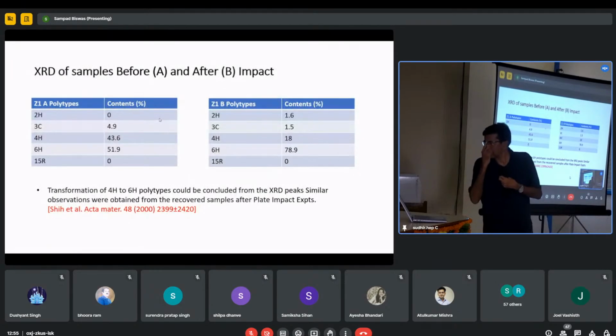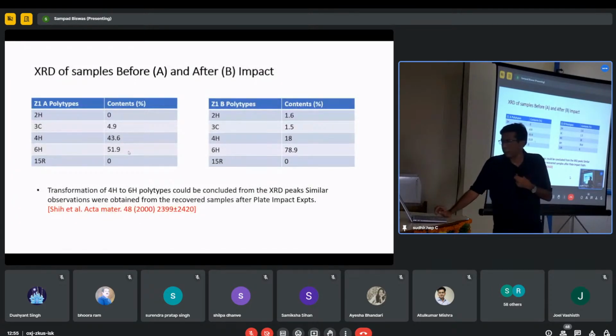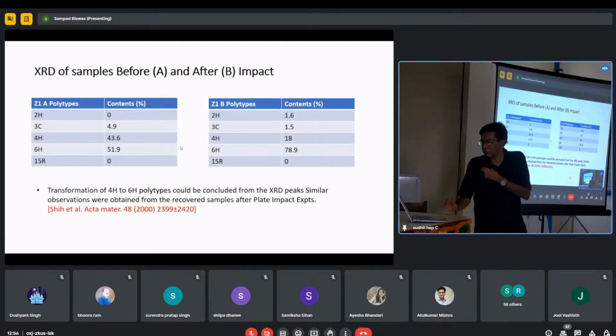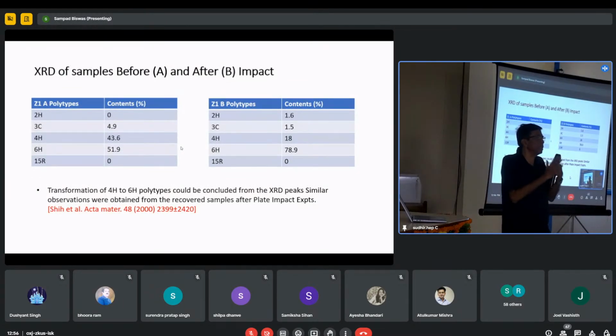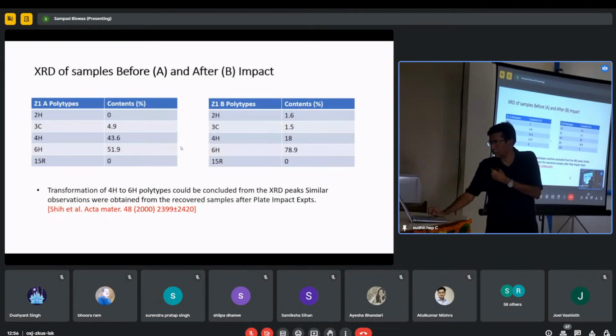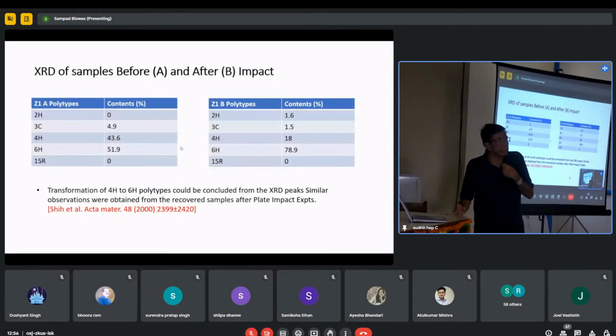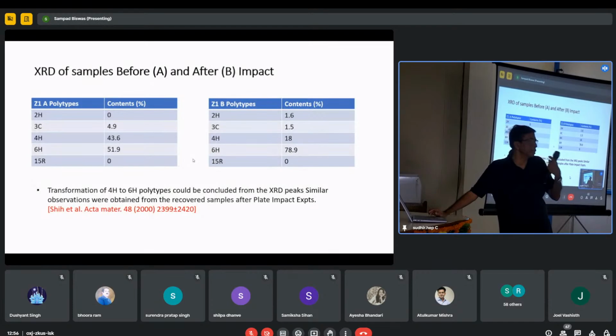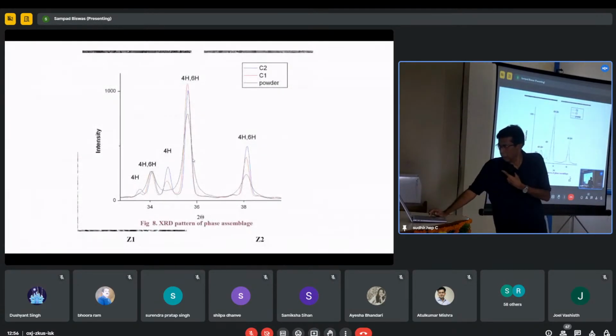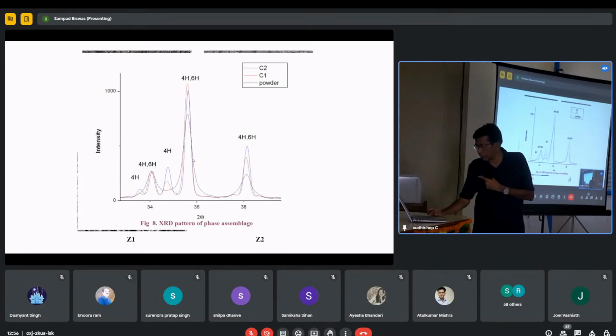Now let us see how it happens. We have analyzed the XRD of the samples after the impact. We can find that initially we started with 51.9% 6H variety. It changes to 78.9%, while the 4H is reduced as well as the 3C. That means these phases have transformed with the help of the shock wave to the 6H variety. That is a very important observation we could find out. This observation was also made by some people earlier, in the year 2000, in the case of another variety of silicon carbide. And it is not only that; we will find another thing.